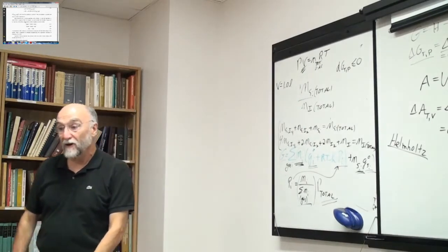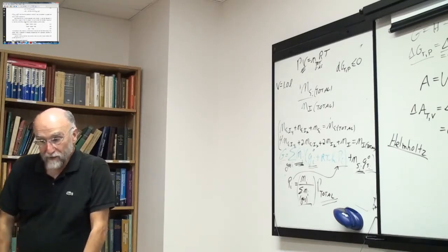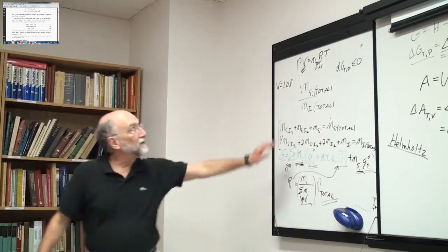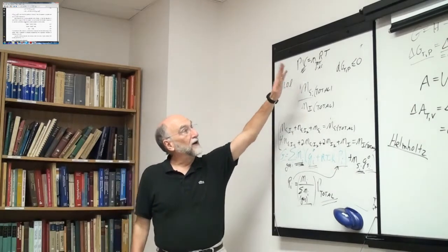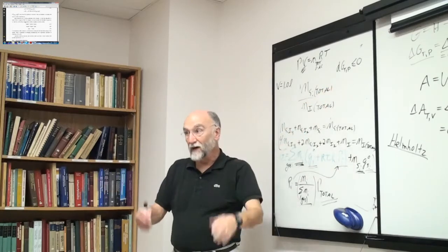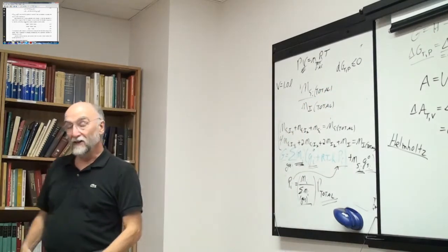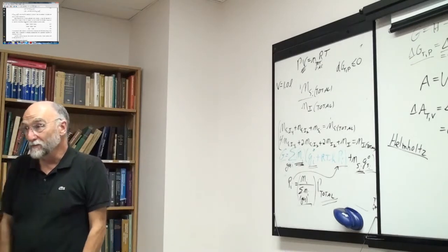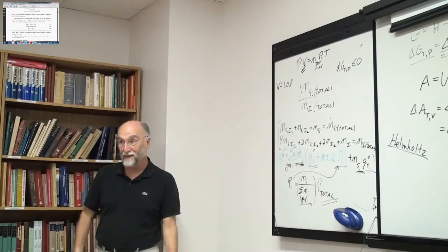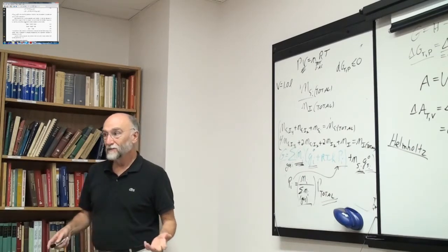No matter what the constraints are, Solgasmix, which is the algorithm at the basis of equilibrium in FactSage, whatever your constraints are, like constant volume or whatever, will guess constant temperature and pressure and will minimize it. Even if the temperature isn't constant, say you want to do an adiabatic reaction, it'll guess what the temperature is going to be at equilibrium, do the calculation, and then see if the temperature is too high or too low, change the conditions, and try it again until you end up with something that's right. So is that clear how it works?